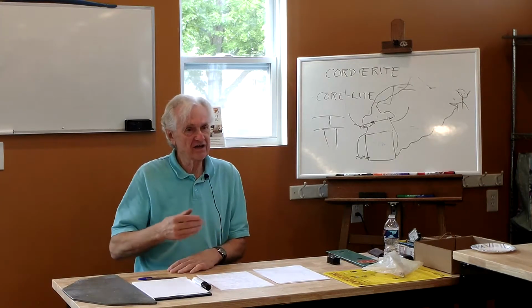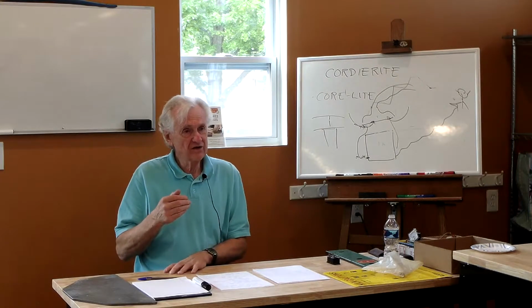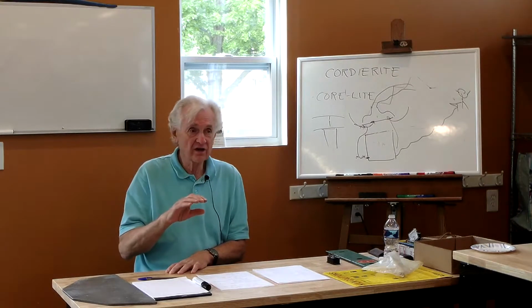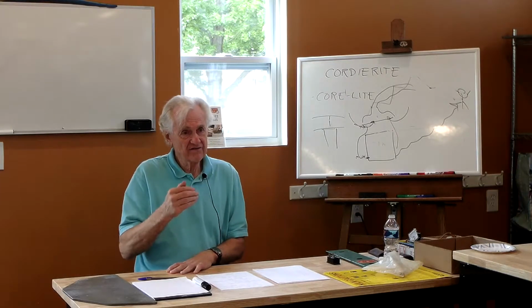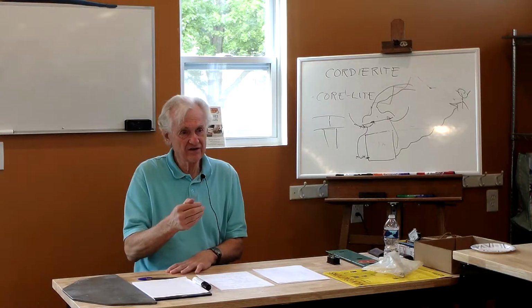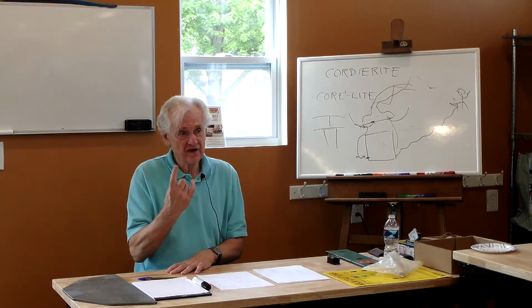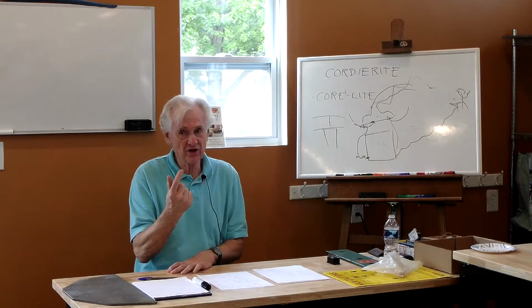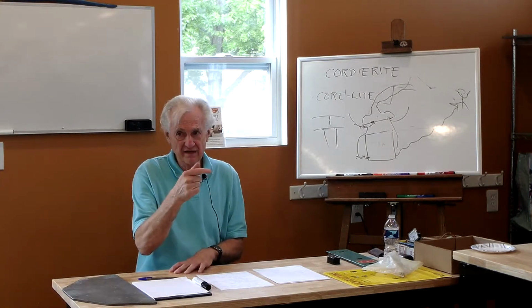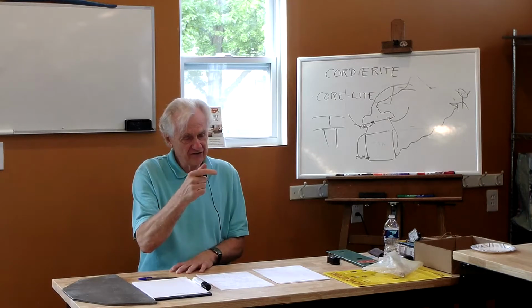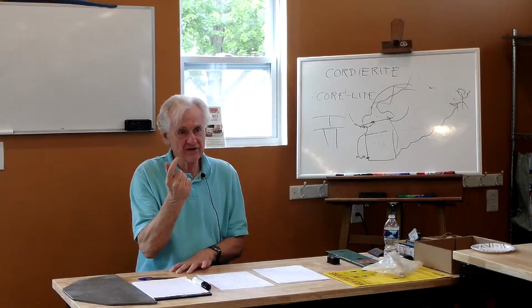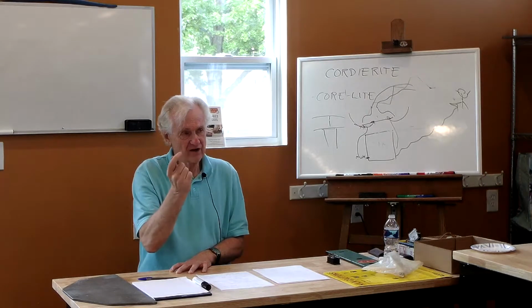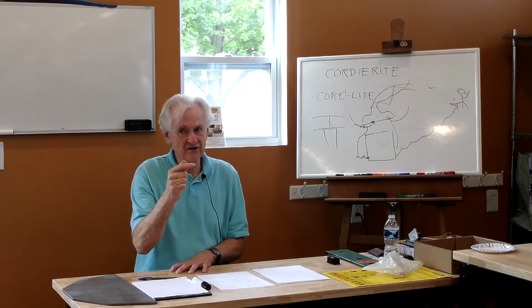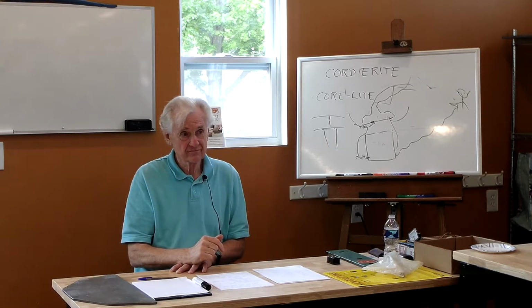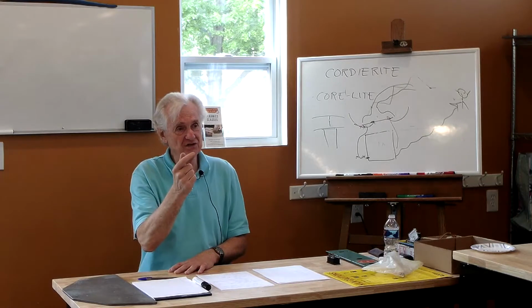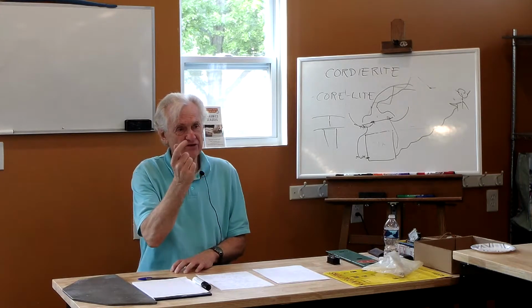And the reason why is, and this is kind of weird, when we're firing by cones, by heat work, when I fire really quickly, then the final temperature to a certain cone is higher than if I fire more slowly. So if I put a number 6 cone in the kiln, and I'm going to do a cone 6 firing, and I'm going to watch the cone bend, if I fire slowly to cone 6 and the cone bends, or if I fire very quickly to cone 6 and the cone bends, when I fire quickly, the final temperature is a lot hotter than if I fire slower. Why is that? Because the cone is measuring time and temperature, so if I've got less time, it takes more temperature to make the cone bend.